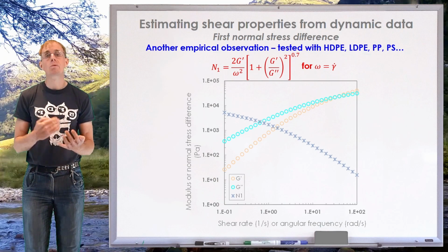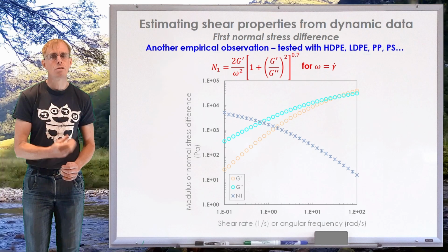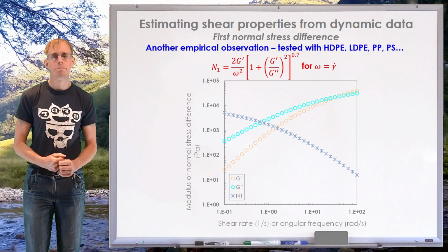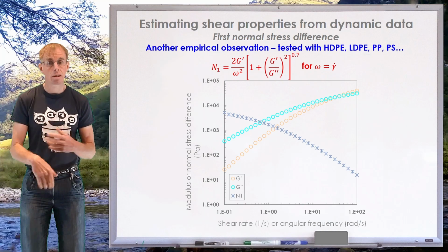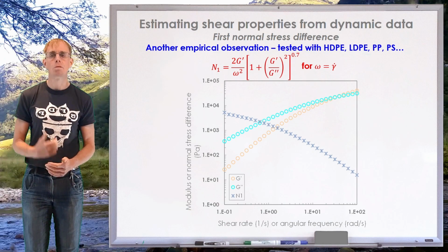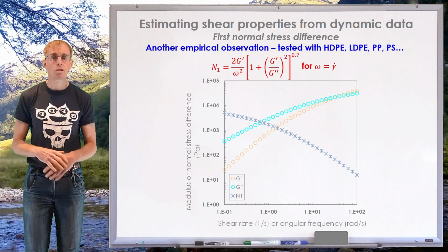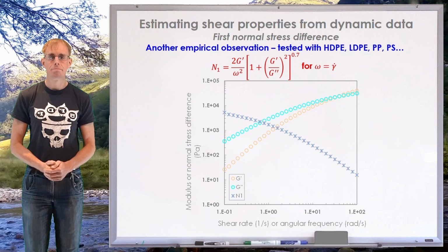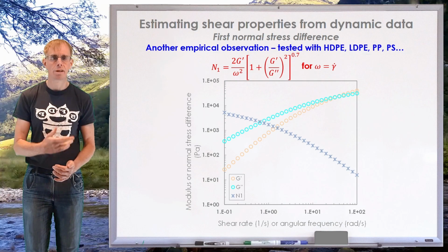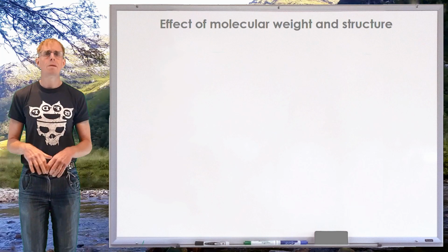Well, if you think back to when we were talking about extrudate swell, Tanner's relationship to allow us to estimate extrudate swell involves N1. And so if we can characterize N1 as a function of shear rate gamma dot via Laun's rule, which gives us G' and G double prime as a function of omega, then we may well be able to make some sufficiently good estimates of extrusion deformation based on that information. Again, it's all about knowing the problem that you're trying to solve and the accuracy to which you need to know the answer. Okay, so we've talked about material properties.